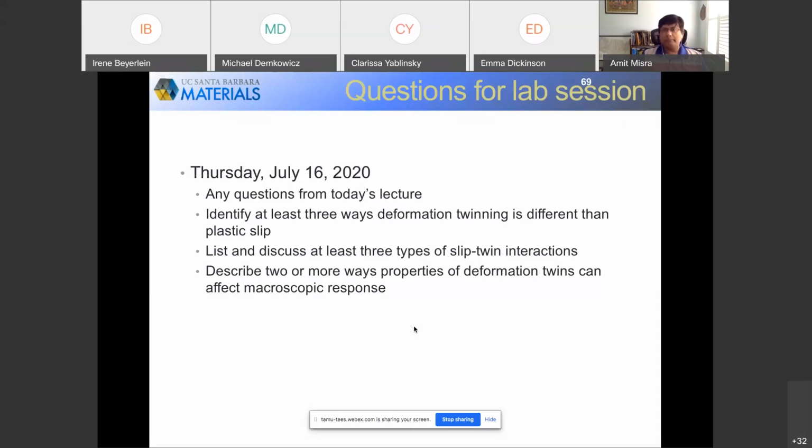Another thing is you also see that there's a coalescence process as the twin moves from forming a stable twin embryo to then being able to propagate into a perfect crystal. So there's a certain critical size. Can't say I know what that size is, but the important point is that there is a critical size. And so the more defective your boundary, with closely neighboring defects, that could enhance or promote the formation of a sufficiently large embryo.